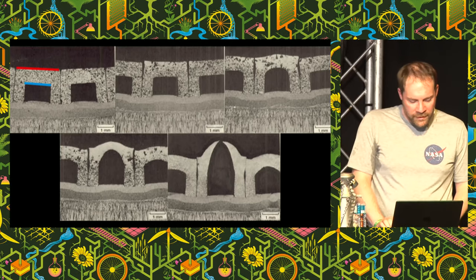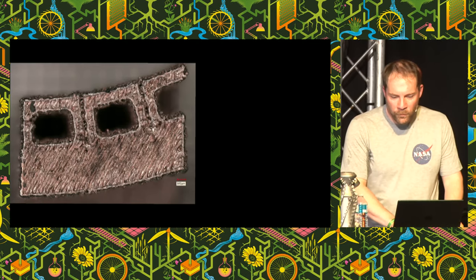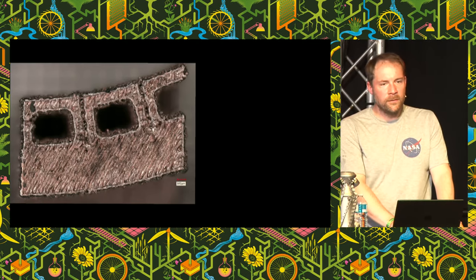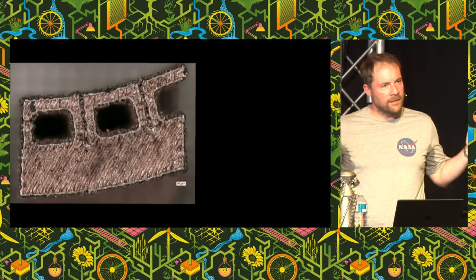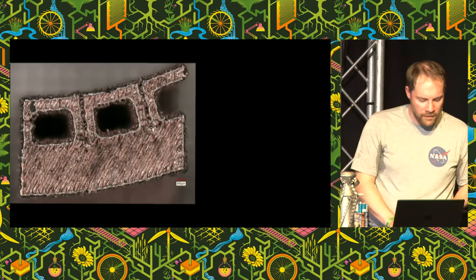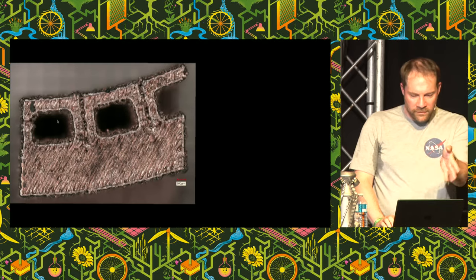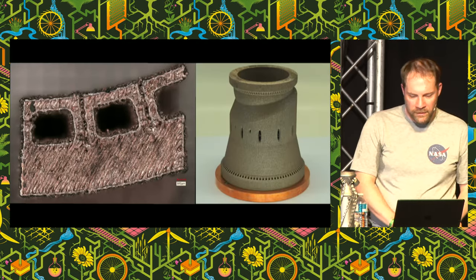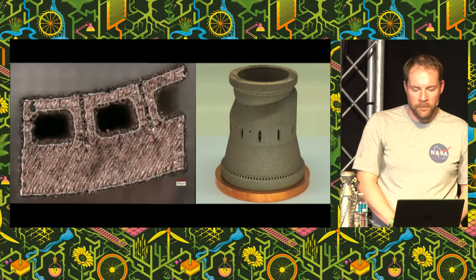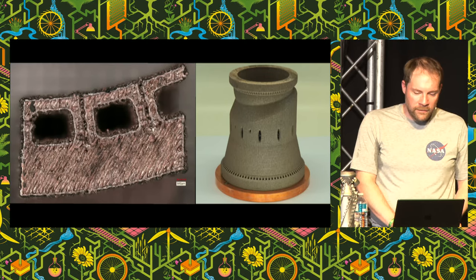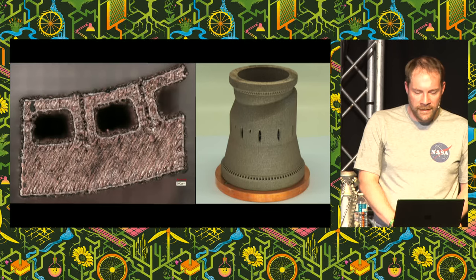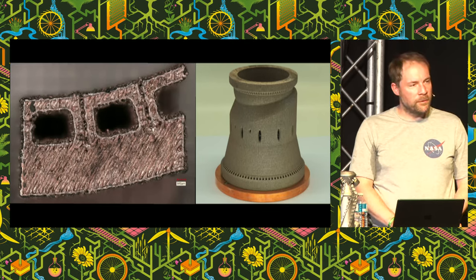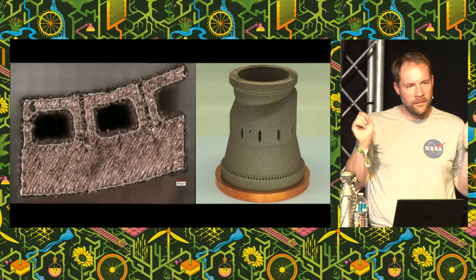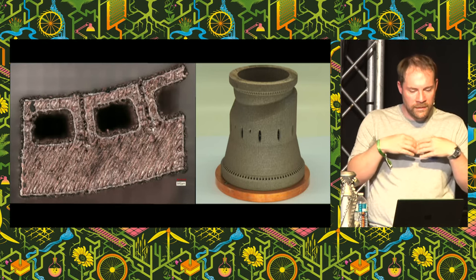So one of the things we've been trying with 3D printing is, why don't we actually print gaps between the coolant channels so that they have enough room to actually elastically deform and then relax again afterwards? And in fact, this is just a small test sample we printed. This is a special alloy called copper chrome niobium, called GRCop-42, but it's an alloy. So it's got very good strength. It's got good thermal conductivity. It's been designed to be 3D printed. And because it's an alloy, it is much less prone to growing pure crystals. All the impurities inside keep the crystals small and keep it more elastic.